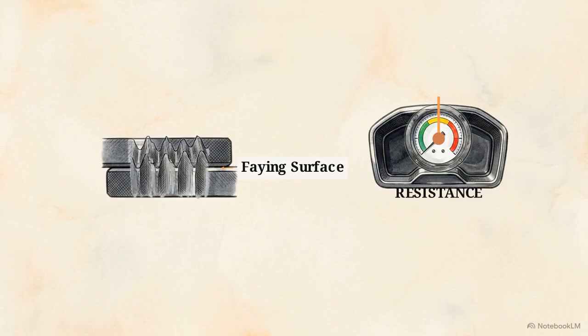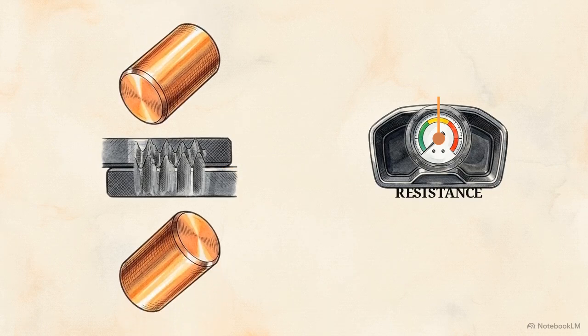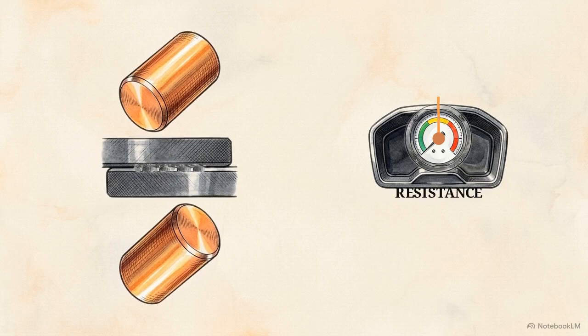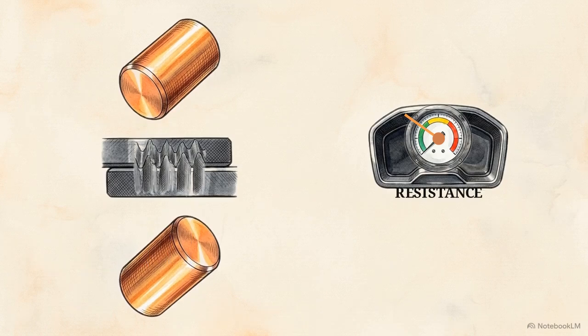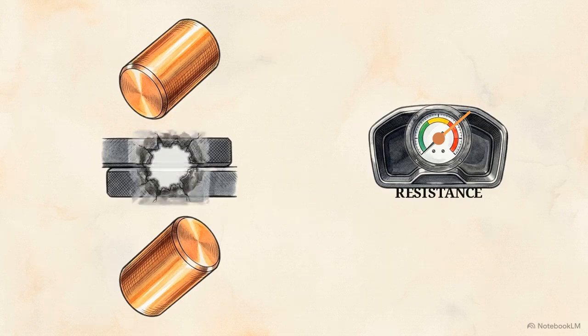Zooming in on the cross-section, we see the microscopic peaks and valleys of the faying surface. When the electrodes apply mechanical force, they compress the metal, crushing those jagged edges flat. This increases the contact area and causes the electrical resistance to drop. If you apply too much clamping force, you suppress the contact resistance. The current flows right through the sheets without encountering enough friction to generate melting heat, leaving you with a weak joint. Conversely, if you apply too little clamping force, the resistance spikes unpredictably. The heat builds up too fast for the metal to contain.